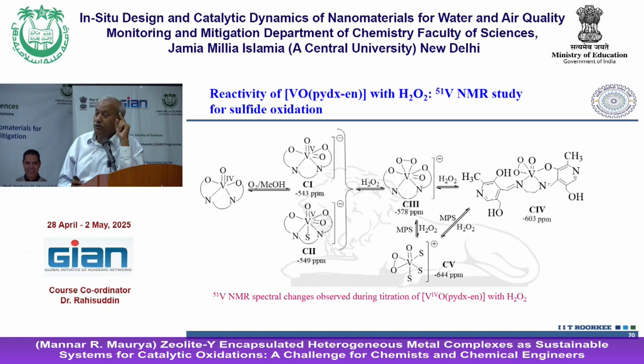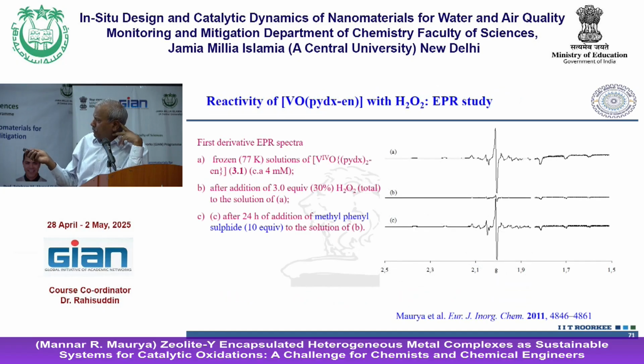EPR for vanadium 4 is helpful. So we have EPR for the compound, with H2O2, and then after adding the methyl phenyl sulfide, you see that the EPR is coming back. So if the compound is not exposed to oxygen, it remains in the +4 oxidation state, and if you add a calculated amount of H2O2 and then of course the methyl phenyl sulfide, you should see the conversion going back to the vanadium 4 compound, not vanadium 5. The only thing is you have to add a small amount of H2O2, then you should be able to see such kinds of changes.